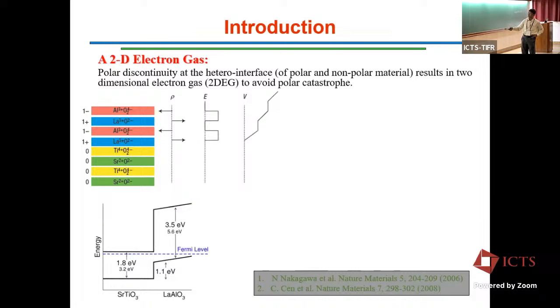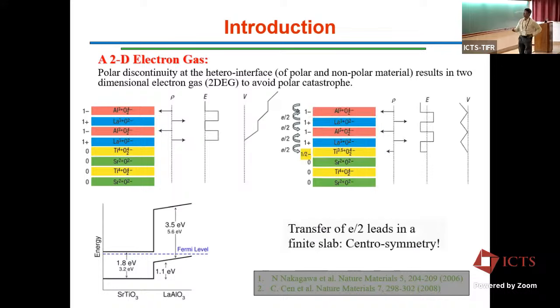So what was believed is that this potential felt by the electronic states of the lanthanum aluminate bends the lanthanum aluminate valence band, for example, going up like this, and that valence band would eventually cross the strontium titanate, which doesn't feel the potential. For a critical thickness, the electrons from here will get doped into there, and therefore you'll have a metallic system because of the doping from the lanthanum aluminate surface from the top with the highest potential to the strontium titanate.